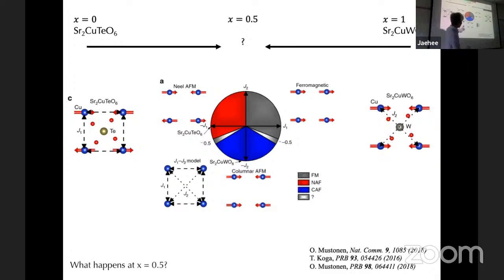and then this disorder gets maximized when x equals 0.5, the 50% mixing here. And theoretically, I think it is one of these papers. Theoretically, they say the tellurium case belongs here, and the tungsten case belongs here. And the 50% case is somewhere here, and then the mean field calculations, they say, well, you shouldn't model that.